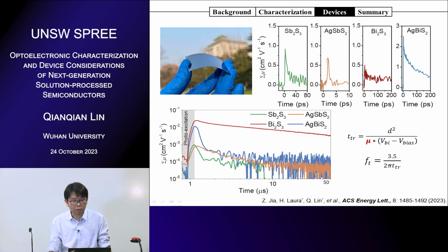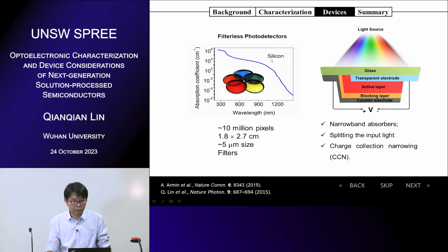And we also work on chalcogenides. So we work on antimony sulfides, bismuth sulfides, and we do a lot of measurements on the chalcogenides, and we want to increase the mobility of these films. If we have very high mobility, you will get very fast charge transport, then you can get high bandwidth photodiodes. So that's the aim for device optimization. And we also do some color discrimination. Silicon photodiodes have a broadband photoresponse, so if you want to detect red, blue, green individually, you have to use a lot of filters.